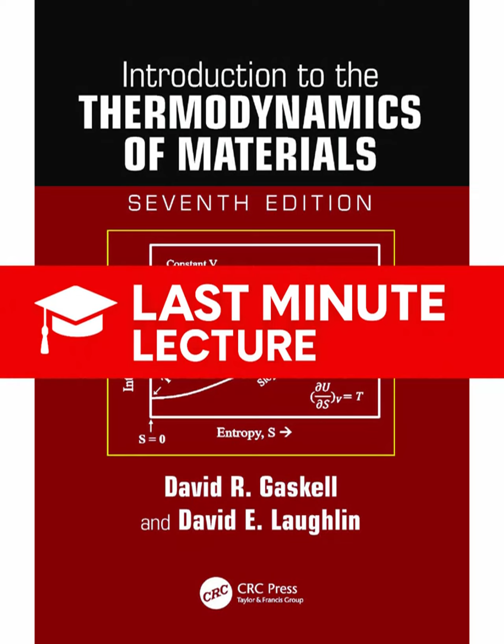It is. And just to connect back to the physics, Le Chatelier's principle reinforces our sign convention. If you have a system at equilibrium, like solid and liquid ice and water, and you add heat, the system has to shift to oppose the change. Right, so it undergoes the endothermic process, which is melting. This confirms that any change from a low temperature phase to a high temperature phase, melting, boiling, is always defined by a positive ΔH.